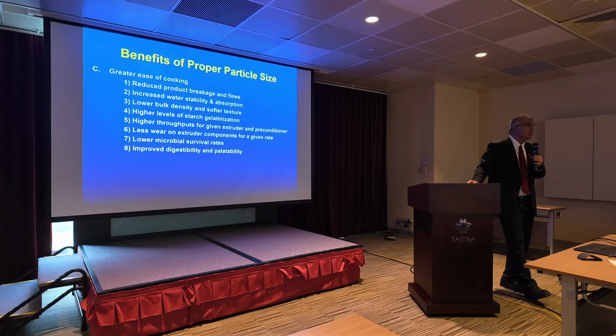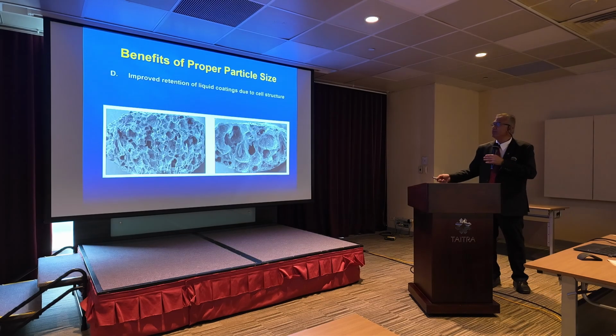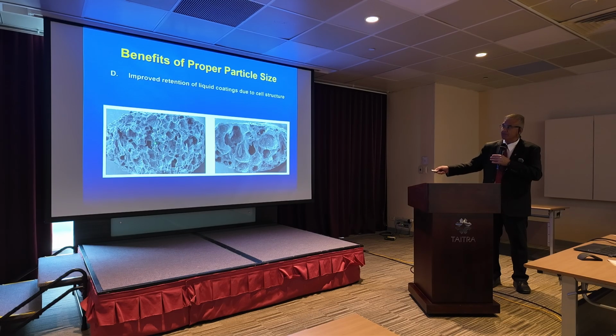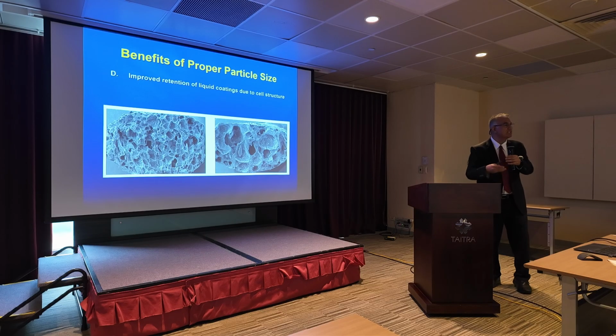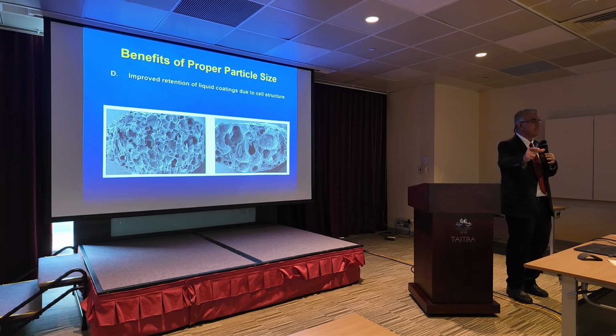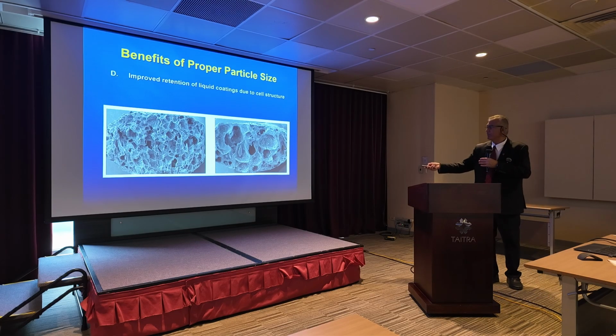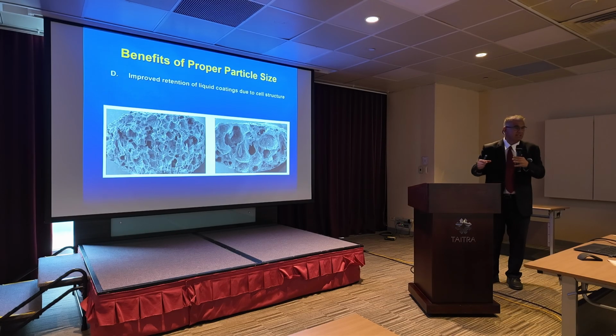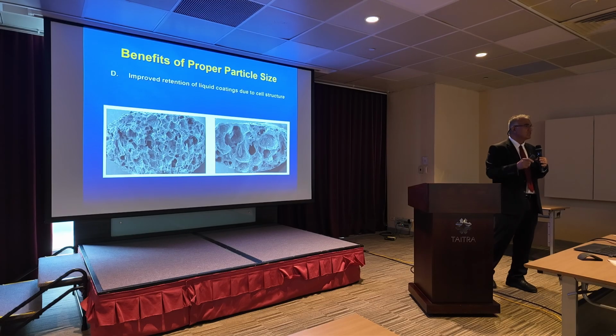And if you are doing a coating on the pellet, make sure of this. This is a fine grind pellet; under the microscope, you can see the cell structure, as compared to this, a coarse grind cell structure. When you coat them with oil, it will go inside and never come out. So you can see the leakage. Sometimes you have feed sitting in a bag and the bag gets oily, oil starts coming outside the pellet, because coarse grinding gives you a poor cell structure and the fat comes out from here, whereas in this case, fat will stay inside.